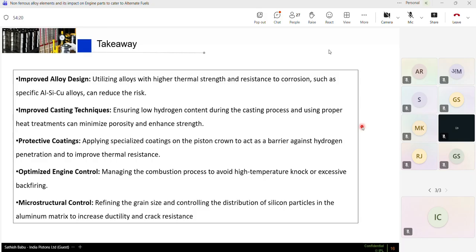Because these kinds of coatings will not create more defects, and this will ensure that our hydrogen does not pass through these intermetallic phases and reduce the thermal mechanical cracks. More beyond that, it lies with the engine optimization and engine combustion area, where the hydrogen engine has a lot of challenges with respect to knocking and excessive backfiring issues.